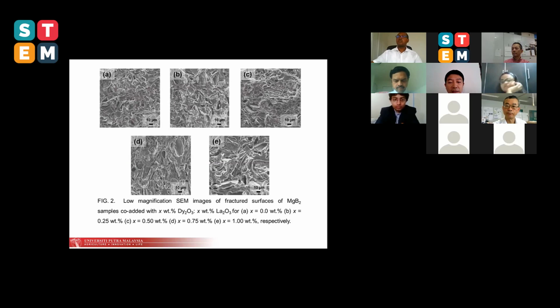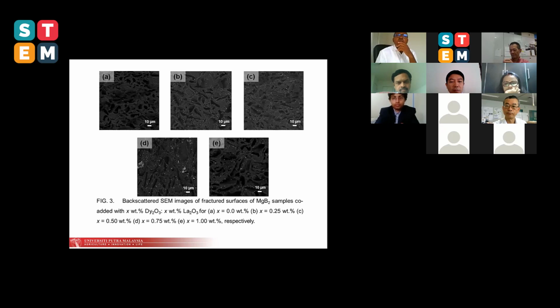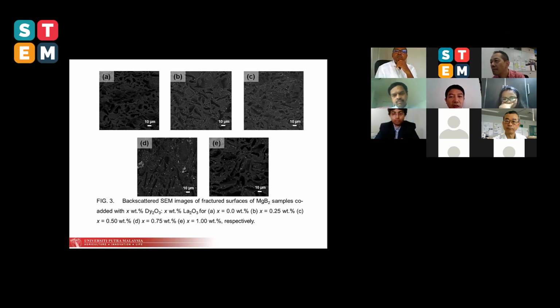These are the SEM images. We know that for in situ samples, porosity is great, and all the samples have a density of less than 50% of the theoretical density. This is the backscatter SEM image. What we would like to highlight here are those white dots, which correspond mainly to unreacted lanthanum oxide and dysprosium oxide. I just want to show that those particles are distributed over the sample.